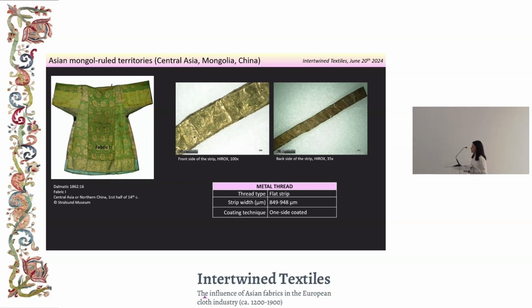This is a dalmatic that has been considered one of the most interesting Tartar clothes coming from Central Asia to Europe. It is actually in Germany, in the Stralsund museum, and it is made with 5 different fabrics. I will show you the results that we have achieved on gold thread in 2 of these fabrics. On this fabric, we have found flat strips, and they have been coated just on one side. You can see the front and the back side of the strip.